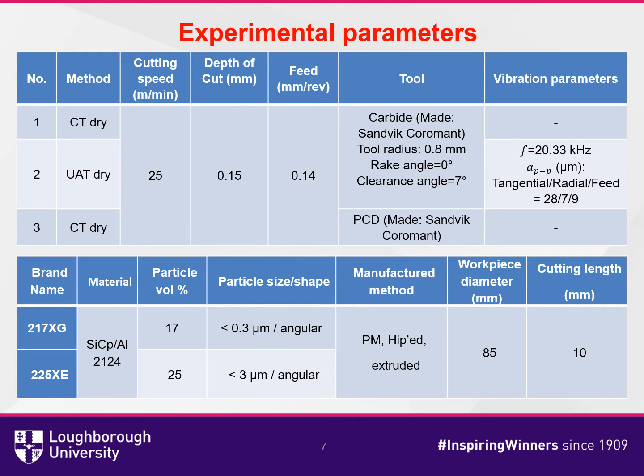The experimental parameters and workpiece specification are shown in the tables. The method was to compare results of conventional turning, represented as CT, with ultrasonic assisted turning using low-cost carbide tools. A third experiment was performed to compare the conventional turning result using high-cost PCD tools. Two different types of silicon carbide reinforced aluminum alloy, having different volume fraction and particle sizes, were also used for comparison.